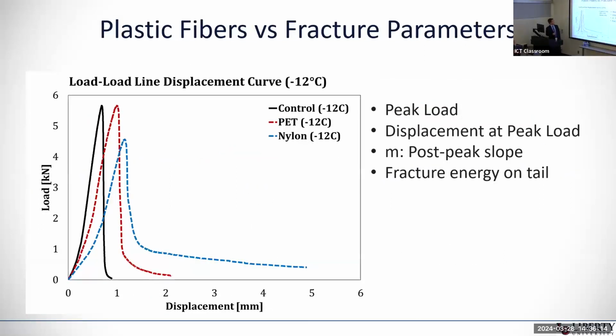Also, when you look at this load displacement curve, one of the things I want to emphasize here is that this black one is the control without any fibers. When you add PET fiber at the low temperature, you can see a significant change in the tail part. And the nylon has a huge improvement of the tail part, which gives us additional fracture energy to completely break this specimen.